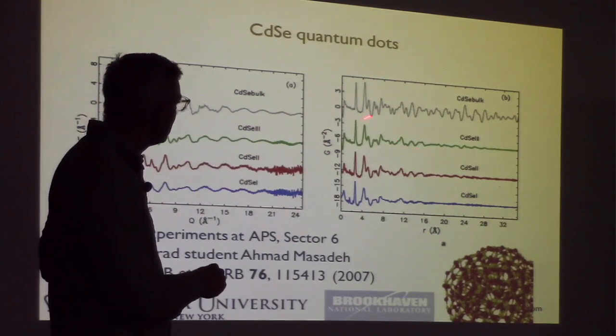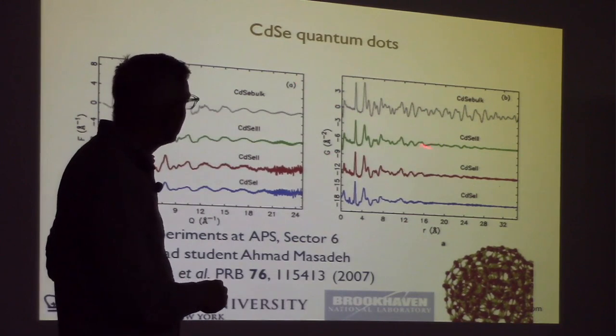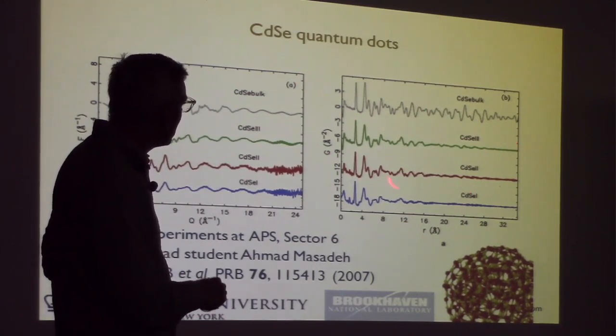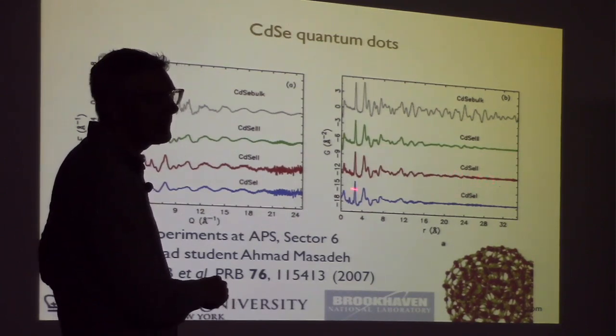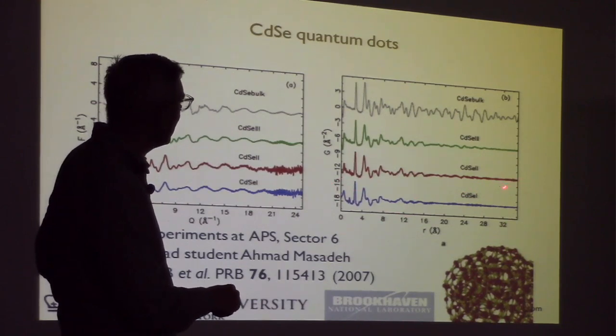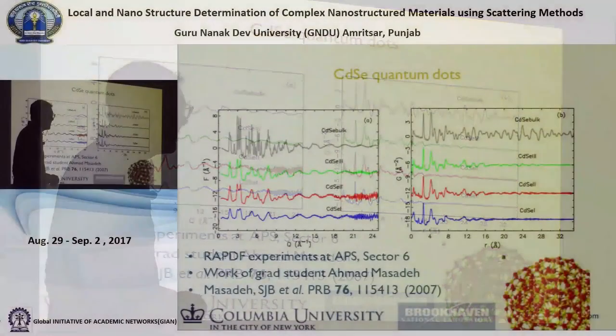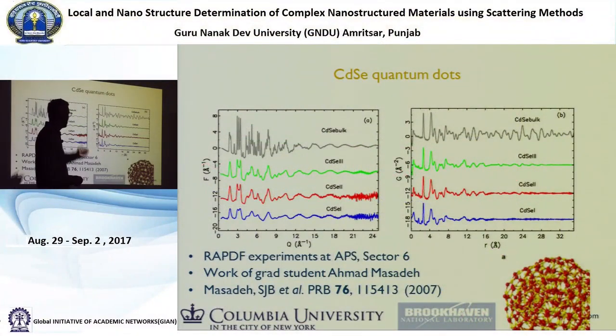And for the nanoparticles, you can see there's an envelope which kind of kills it. So for this one here, I can still see a signal out there, but it's getting weak. This one here, there's a signal, and it's kind of gone by 30. So this is my 3-nanometer diameter nanoparticle. There's no signal out after 3. And this is my 2-nanometer diameter nanoparticle, and there's no signal after 2, but there is signal below 2. So the PDF, just even looking at it without doing any modeling, I can immediately tell you how big your nanoparticle is.